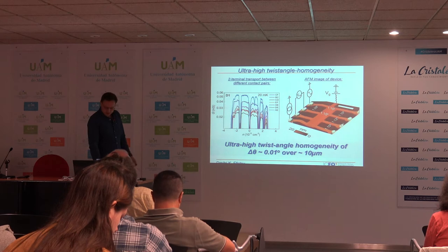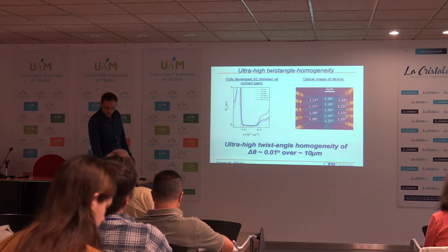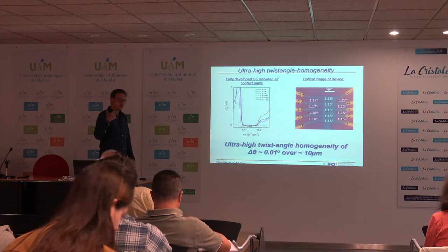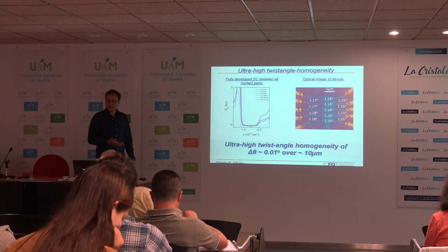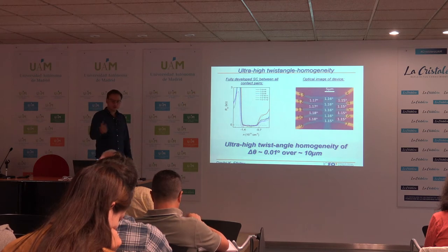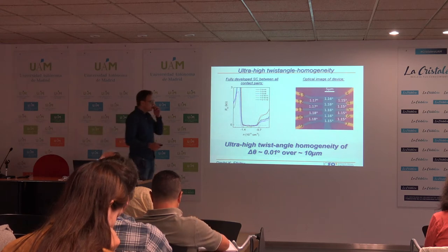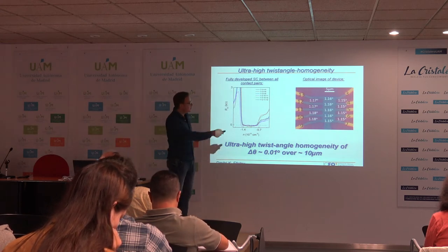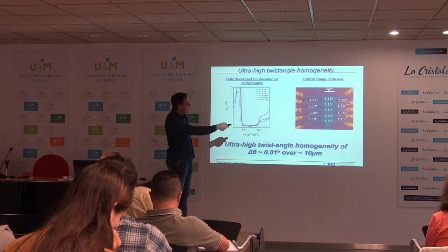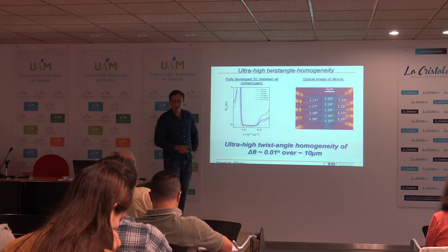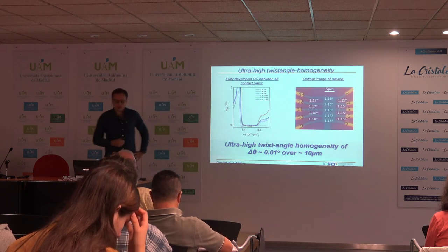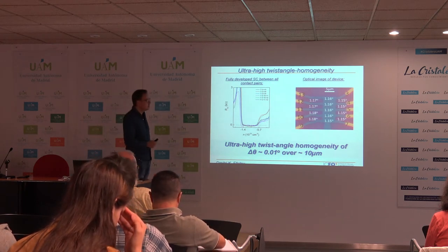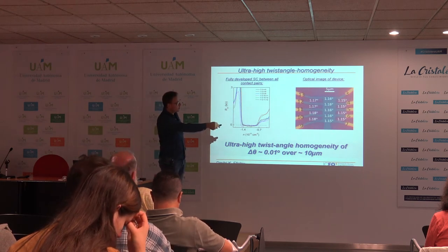And of course, this question will arise: do we see all these effects that are described in all the regions of the device? Do we see superconductivity in every region of the device if we use different contact pairs? So this is just to give you another device which we made recently. It is fairly large, about 6 micrometers broad and about 30 micrometers long. This is 5 or 6 times bigger than the typical devices which we made previously, or which are made in the group of Pablo, for example.